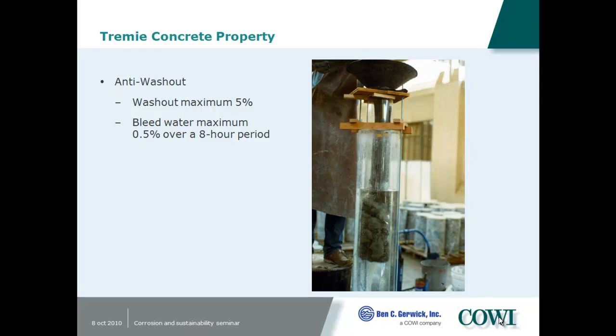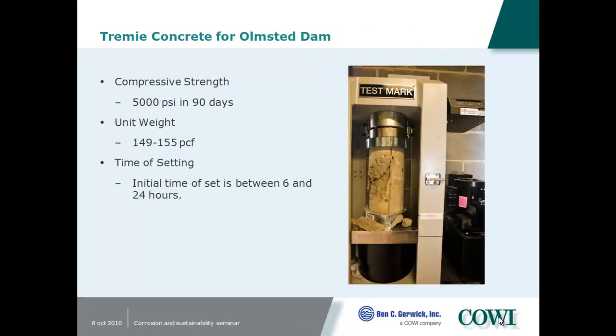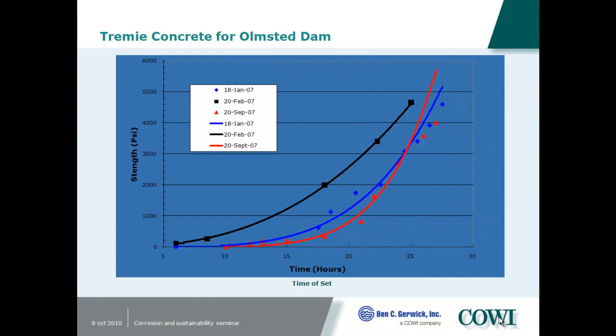Also, when you put in the anti-washout admixture, it also decreases bleeding, so there's better adhesion with the reinforcing steel. There's less top bar effect of that. We, of course, monitored the compressive strengths. These were just the design properties. On this particular job, we had an initial set time between 6 to 24 hours. We wanted to keep it workable while it's being placed underwater.